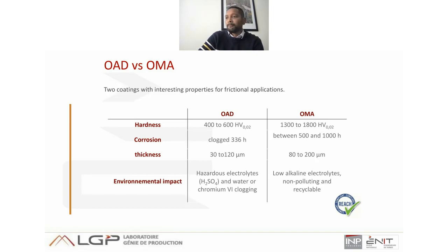So I propose here different parameters in these tables, different mechanical properties of OAD and OMA, like their hardness, and we can see that they are very different from OAD to OMA. Also the coating thickness, and we also present the environmental impact of these two processes. We note that the OAD uses hazardous electrolytes, especially hexavalent chromium, and the OMA is more in line with European regulation.